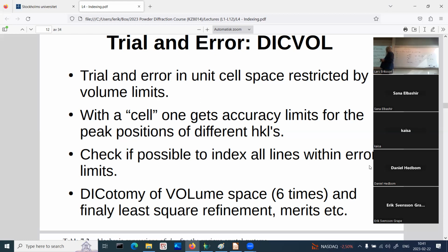And if yes, then we found that. Dicvol and the versions of Dicvol we have available are exhausted, and we say that the unit cell A, B, C should be from 5 to 25 angstrom. It will try, I think it's divided in 0.5 angstrom steps, all possibilities.